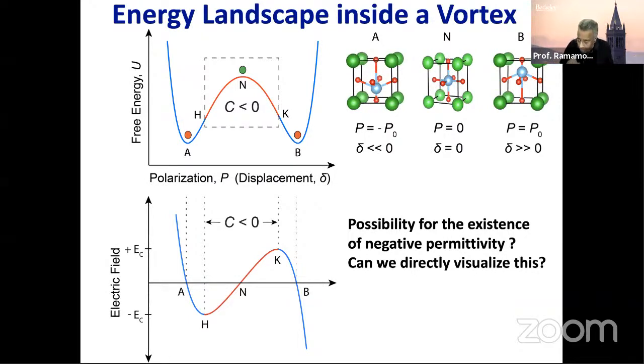Before I do that, I want to give you some very simple physics background. So if you can visualize these things, these materials at high temperatures, they are in a paraelectric state. And so if you look at the free energy versus order parameter, that looks like a parabola, with the lowest energy being at 0 polarization. Of course, there is no polarization at high temperatures. On the other hand, if you go to very low temperatures, below the transition temperature, you will start to see this double well-like structure. Very classical Landau physics will explain this for you.